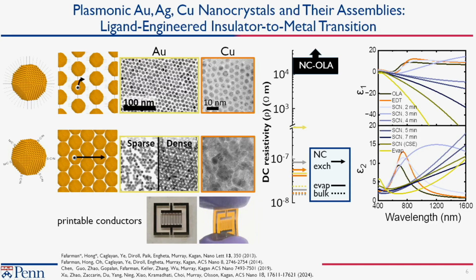It gets close to what you measure in an evaporated film in the lab. Obviously, those are polycrystalline films, and you get within a factor of 3 to 10, depending upon the composition of the material. And so we can make very good conductors out of these materials. I won't talk about those today, but we do that. There's a whole component where we're working on RF electronics and the opportunity to build devices using these kinds of materials.